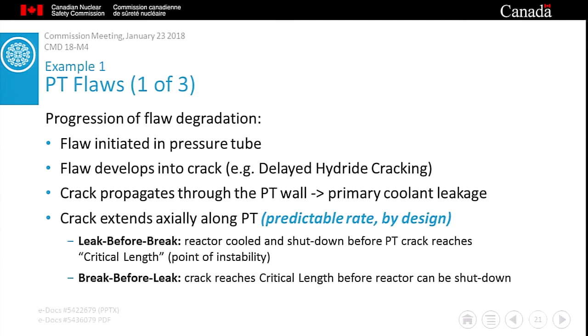Let's start with example 1. The vast majority of pressure tube flaws are fairly innocuous. Once created, they exist as mere blemishes on the pressure tube surface, having neither economic nor safety implications. However, a very small fraction of flaws could potentially have serious consequences. First, the flaw is created during normal reactor operation. If local stresses and the hydrogen level are appropriate, this flaw can become a small crack.